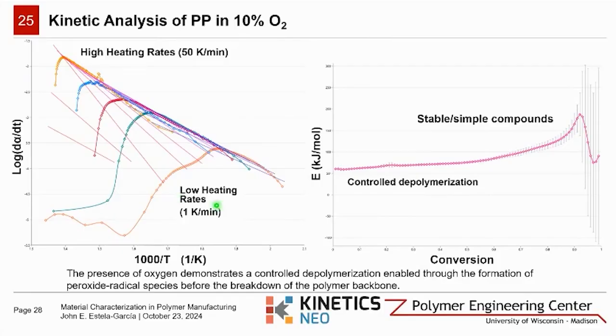The presence of oxygen facilitates controlled depolymerization through the formation of peroxide and radical species. And these reactive intermediates significantly lower the activation energy that is required to break down the polymer. While this complicates the kinetic modeling, it provides valuable bounds for determining kinetic parameters. This range of values is crucial in developing an understanding of polypropylene degradation.